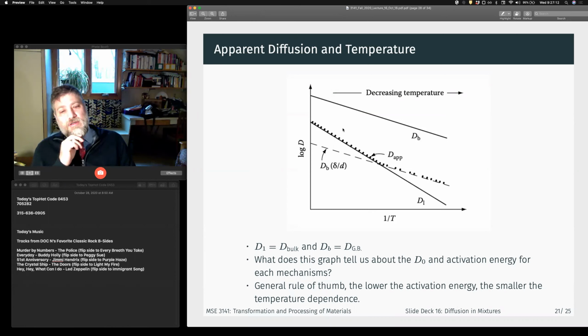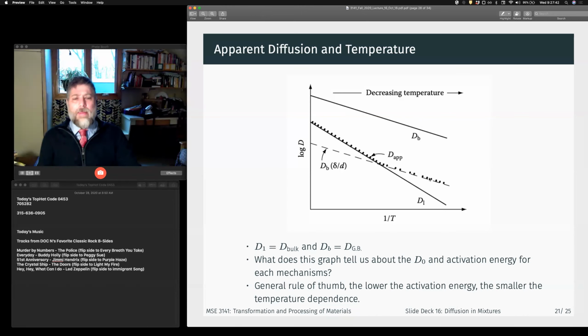Here's our bulk. And what we see is that at high temperatures, this is the inverse temperature, so as we come close to 0, this becomes higher and higher. At higher temperatures, the apparent diffusivity is very, very close to the bulk. But then as we get to lower temperatures, the effective grain boundary diffusion kicks in, right? And there's actually a deeper message here than just the relative diffusivities.